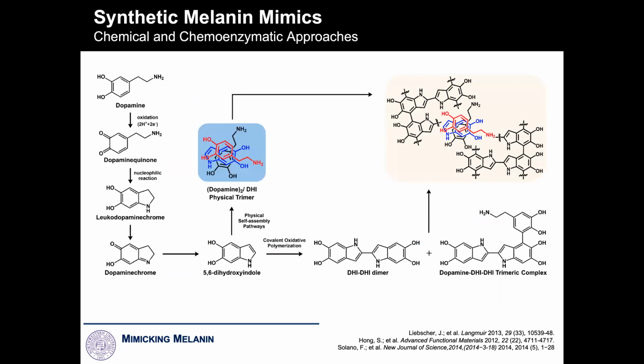To give you an idea of one of the synthetic procedures that we use, and we use many, but to break it down to one of the more common ones that people use in this field, is to take dopamine and then cause it to oxidatively polymerize. So we initiate this process by increasing the pH. And we go through intermediate cyclization reactions, and then cross-linking begins. And the cross-linking reactions are radical reactions as a result of these oxidative conditions.